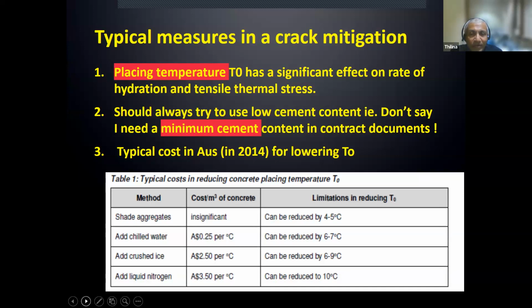And also, don't trust your fly ash or silica fume. As I said, they sometimes produce more heat than ordinary Portland cement. In Western Australia, about 20 years ago, the guy said marine cement, 80% slag. Some clients poured it, and the concrete cracked the next day, where they didn't have a single problem with ordinary Portland cement. I still work for the Western Australia Water Corporation after 20, 30 years. Sometimes they crack because they send it to the mill to grind it very fine. So fly ash and slag can produce more heat than ordinary Portland cement.